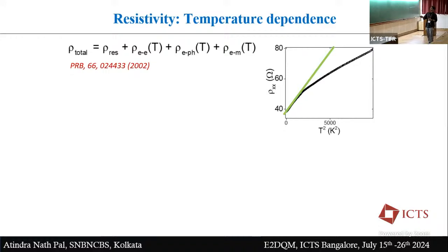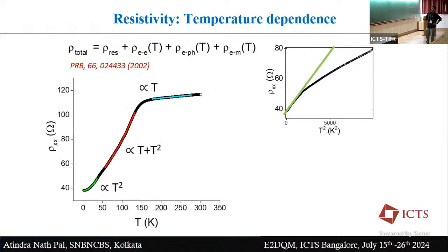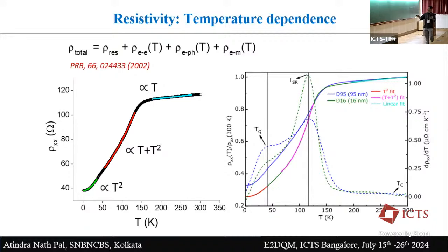So you can see, if you plot the resistivity data as a function of T square, it shows very nice Fermi liquid type of behavior, till like 40 Kelvin. And you can also fit the whole data: the first part is T square, then the second part you have both T plus T square type of term, and the high temperature part is dominated mainly by the electron-phonon term. Then what we did, we fit the data in both the devices, and you can see the hump is present in both cases, and you get almost similar characteristics.